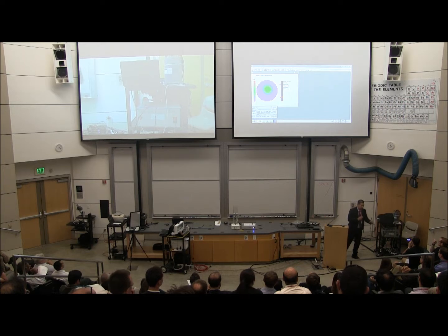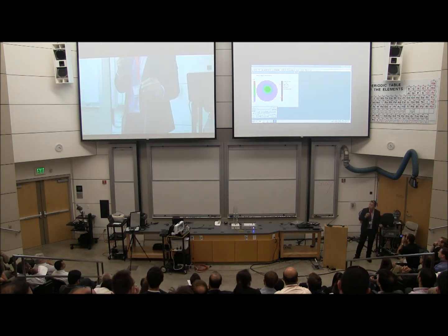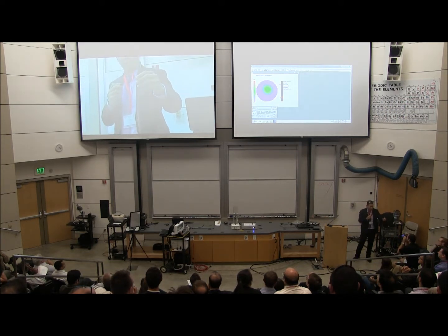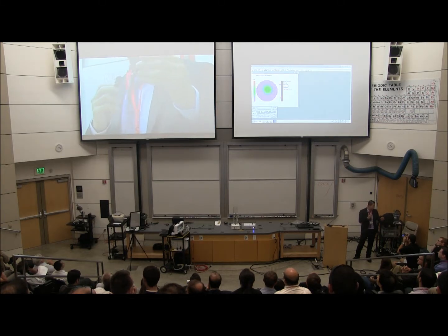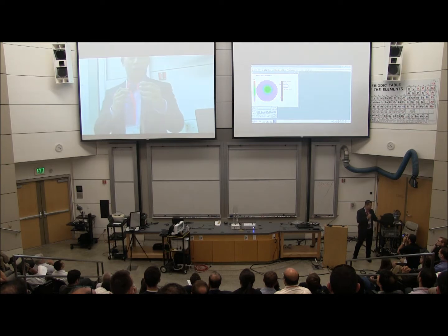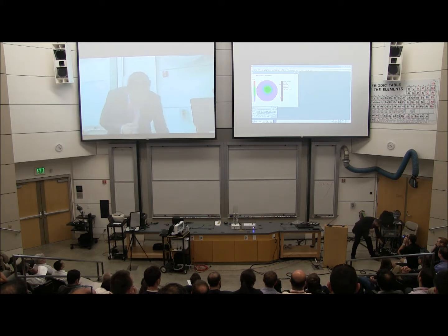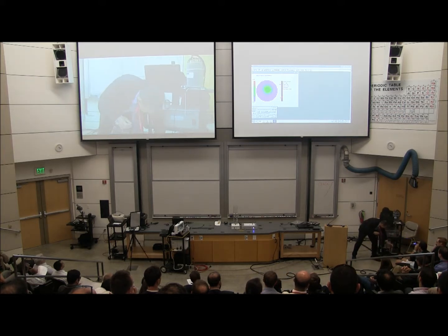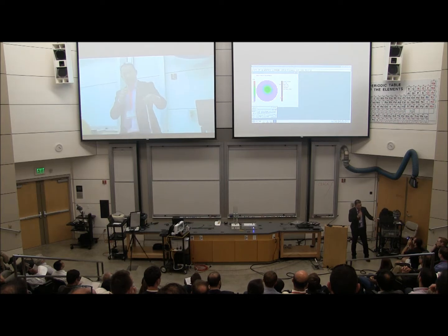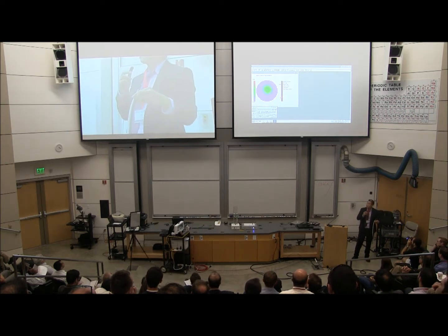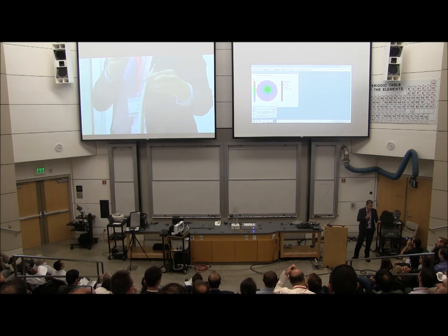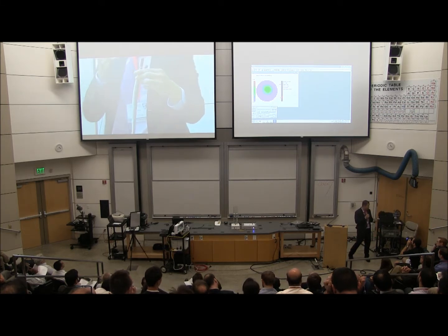So can you zoom in on this real quick? To facilitate this demo, we found some essentially very flexible rubber hose, if you will. So this is a pristine rubber hose, and Sumit will show you that when he inserts it into the sensing array and tries to stretch it by hand, you won't see much of it. But we've also had an identical rubber hose that we've pre-coated with a carbon nanotube-based thin film, and that's been patterned on the surface of this coating to enable us to detect strain.